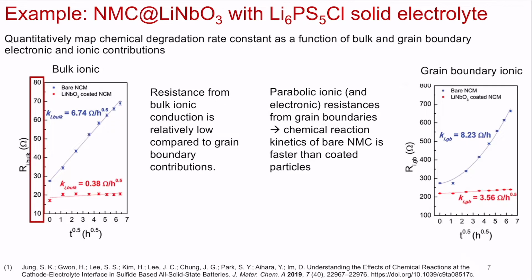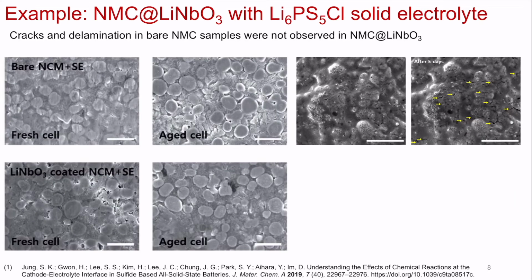So the saying is, it's a dynamic process which changes from cycle to cycle, and it's not, well, it is obvious. Once you understand what the decompositions are, you can predict and screen if these trends are going to continue. And for the oxides, it's mostly passivating. But for the sulfides, it's not necessarily the case. It's quite reactive.